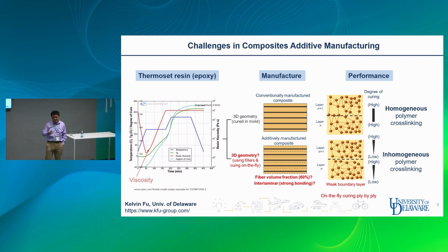Suppose we can cure the resin instantly, and we place one layer, so in this layer all the monomers have been cross-linked. If we place another layer on top, the top layer cannot form a cross-linked network with the bottom layer. This is well known. That's why with any type of layer-by-layer printing, the material will have very weak interlaminar bonding strength in between. Those are the two major challenges that I think prevent the current development of 3D printing of composites.